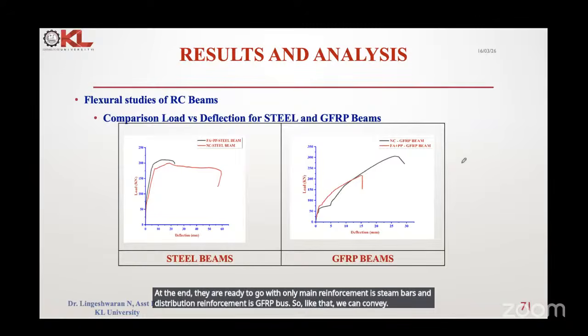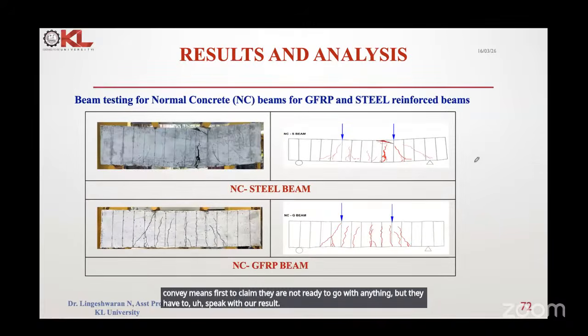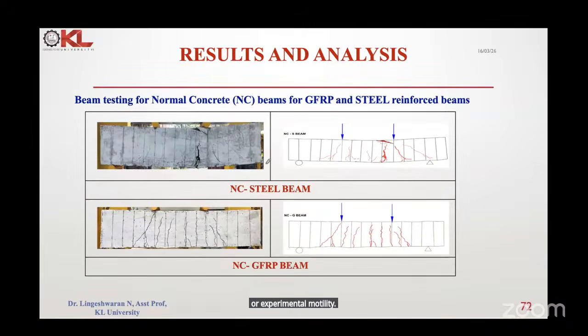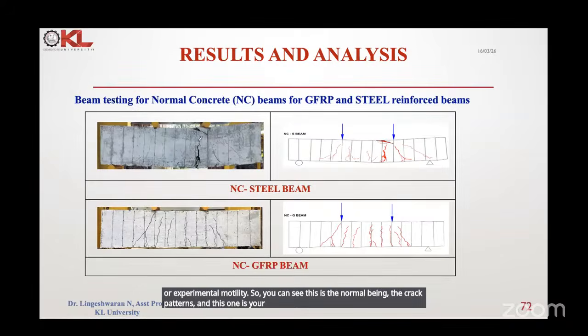We can convey means that at first they are not ready to go with anything, but we have to speak with our results, our experimental work, everything. So you can see this is the normal beam crack pattern, and this one is your GFRP beam crack pattern. You can see clearly the normal beam gets cracks here, but this one is the normal distribution. Like GFRP, we added some 20% of fly ash.